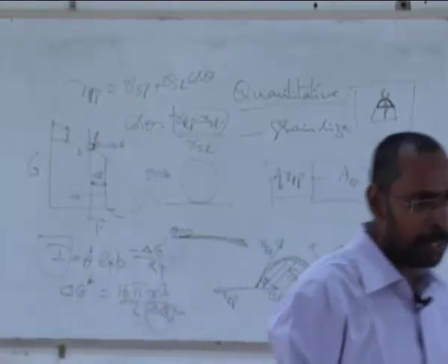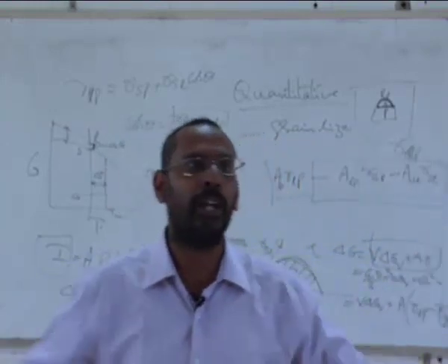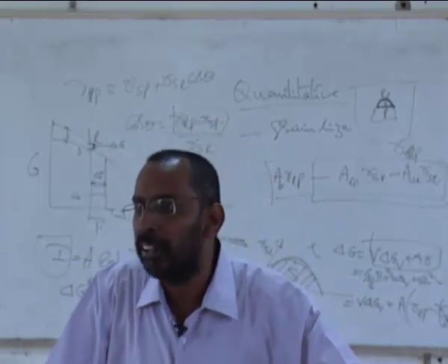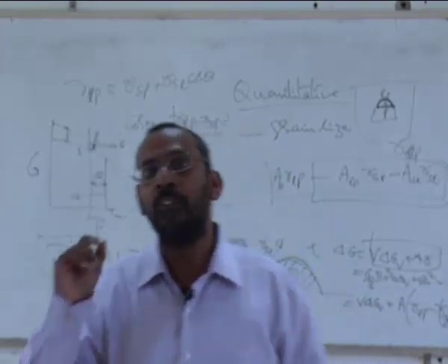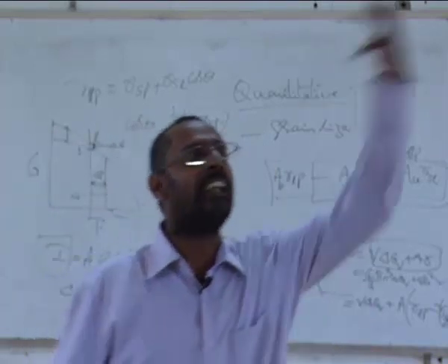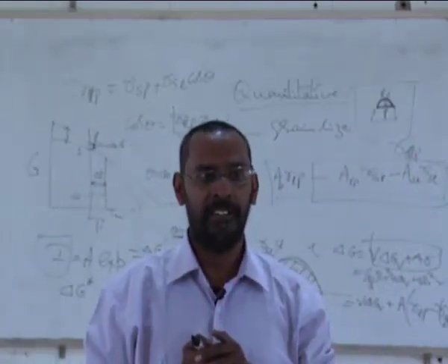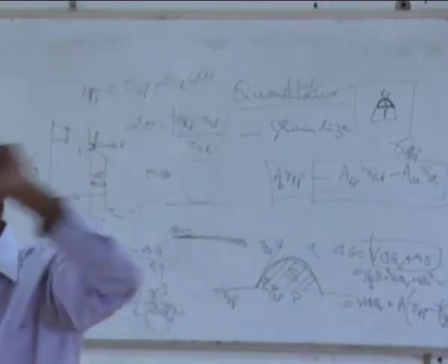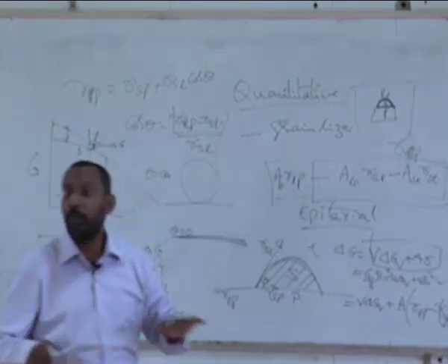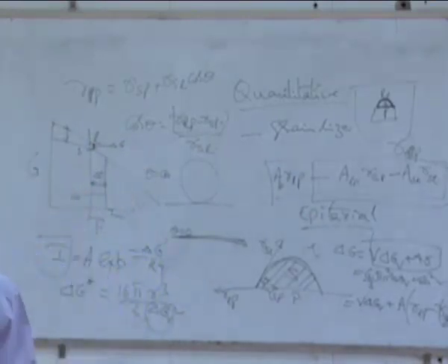Otherwise, it will not. That's why I cannot take a liquid of, let's say, aluminum and simply take some sand particles, drop them into liquid aluminum, and expect them to work as nucleating sites. They will not work. I need to add those particles which have similar crystal structure to that of the solid that is nucleating. What is the solid that is nucleating? It is FCC aluminum, let us say. So my particle should have similar crystal structure to that of FCC aluminum. Then the interfacial energy will be very low, because that is when we call it epitaxial growth. So gamma SP will be lower only then, and when that happens only will you have this.